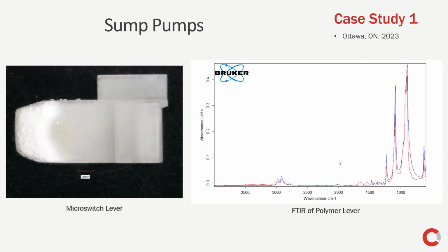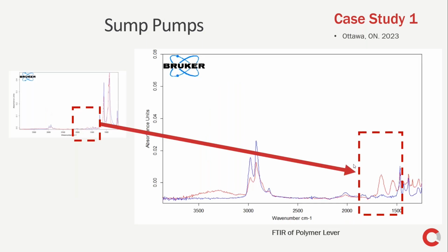What we found during the FTIR analysis of that polymer is, around the 1500, 1700 wave number mark, we found some evidence of degradation. We can see that highlighted here, where these two peaks that I'm highlighting are clear evidence of structural degradation in that polymer. And basically that tells us that something inside had damaged that material. Now, when we do the analysis on something like this, we know that there's no water coming into the float switch that could have done this. And it doesn't look like it's a liquid because there's no damage anywhere else.